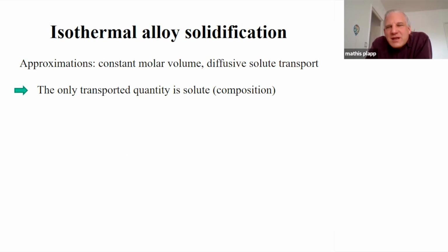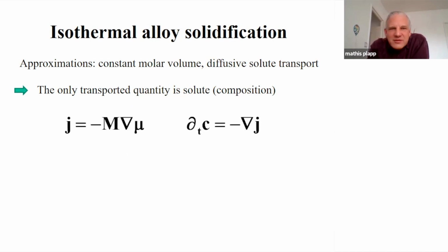So suppose that we have a mixture that crystallizes. So this is like isothermal solidification of an alloy. And if I make again the approximation of constant density and I neglect fluid flow, then the transport of solute atoms is diffusive. This is the only transport phenomenon that I need to take into account. I have got a solute current that is now driven by the gradient in chemical potential. And I have a balance law for the local composition, which is the divergence of the current. So this is nothing but mass conservation. And here, this is the classical thermodynamic law of chemical diffusion. It's the equivalent of Fourier's law for heat conduction.